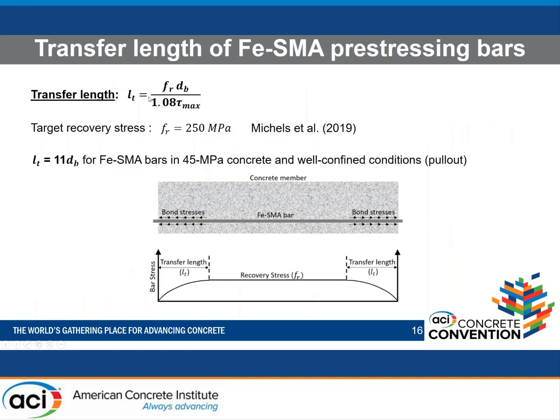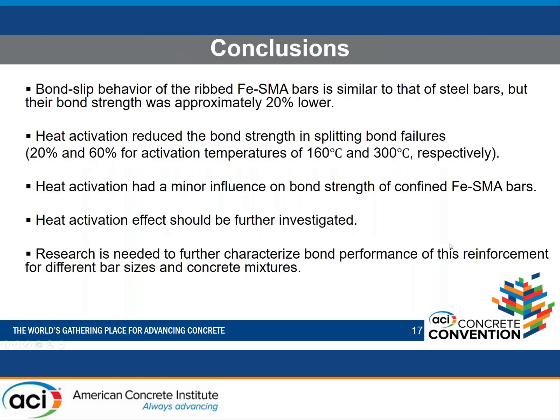So now with this expression, the transfer length expression, we wanted to get an idea about the transfer lengths for the SMA bars, which were used for this study. And I'm using here a target recovery stress of 250 megapascal, which was recommended by Michels et al. For this specific bar, we got a transfer length of 11 bar diameters for a 45 MPa concrete. This is, of course, for well-confined concrete. And of course, this is not a design value. This is an estimation, a minimum requirement, based on this specific bar, based on this specific material. If we want to expand later for design recommendations, different bar diameters will be chosen, and also factors of safety have to be taken into consideration.